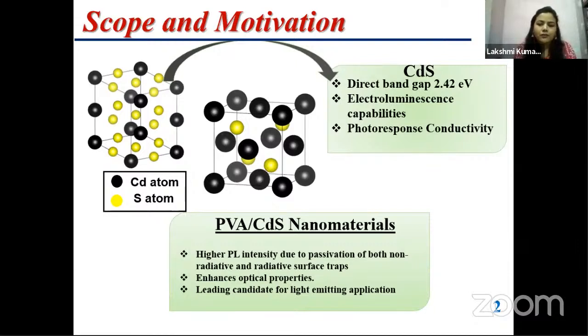But we wanted to achieve some tunability and enhancement in PL. So we have capped it with polyvinyl alcohol, which is an insulating polymer. Through literature survey, we got this idea. It enhances PL intensity due to passivation of both non-radiative and radiative surface traps of this nanomaterial, and it also enhances its optical properties, so it can be a leading candidate for light emitting applications.